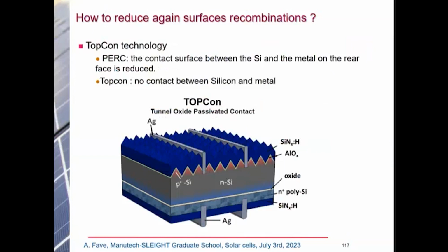On the backside, you deposit your oxide, your passivation layer. Then you deposit polycrystalline silicon or amorphous silicon, anti-reflective coating also, your contact, and you make annealing also. So your amorphous silicon becomes polycrystalline silicon. Here you have a good contact, of course, between silver and highly doped silicon, but no contact of your silver or aluminum with silicon.